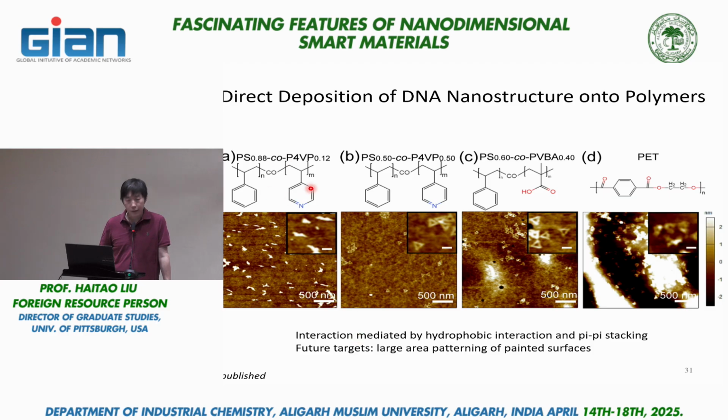DNA nanostructure is very hydrophilic, and most of the polymers are hydrophobic. So traditionally, people didn't think about those two as compatible. But our recent work, still unpublished, seems to suggest some kind of hydrophobic interaction and incorporating charge-charge interaction can stabilize the DNA structure even if you are working with a hydrophobic polymer substrate.